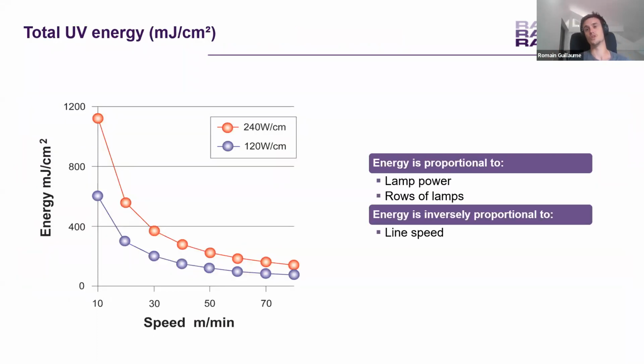If we start with the total UV energy, which is in joule or millijoule per square centimeter, this energy is, of course, proportional to the lamp power. On the left, you can see two curves, one with a lamp of 120 watt per centimeter in blue, and in red, one which is 2 times more powerful at 240 watt per centimeter. If we take, for example, a speed of 10 meters per minute, you can see that with the first lamp at 120 watts per centimeter, you reach a total energy of 600 millijoule per square centimeter.